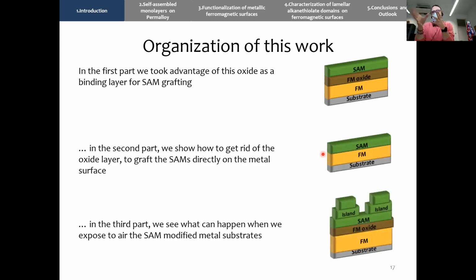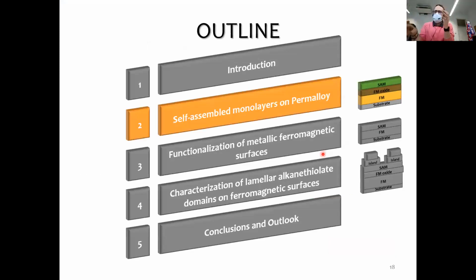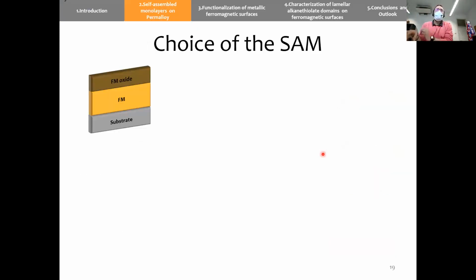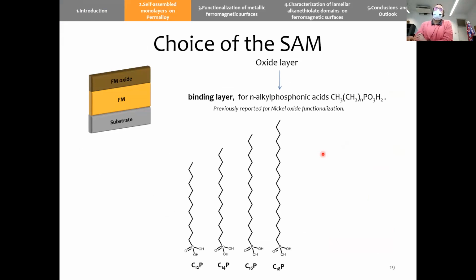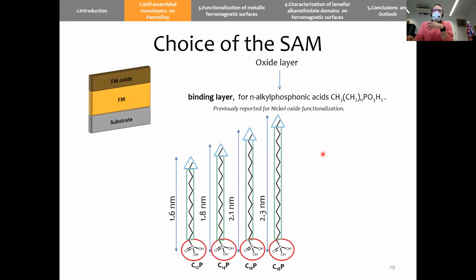And in the third part, a strange effect that we observed while developing the second part. So continuing, we can go. So we have an oxide layer. We know that phosphonic acid monolayers can be grown onto oxide surfaces. So we decided to work with this family of alkyl phosphonic acids of increasing chain length.